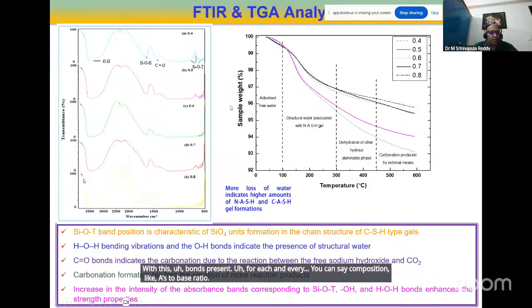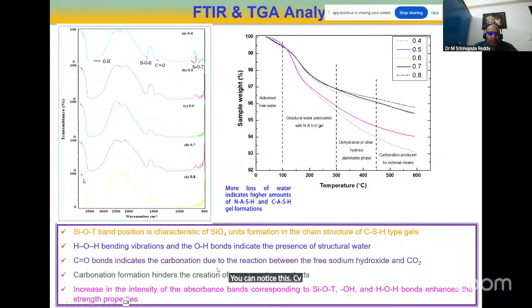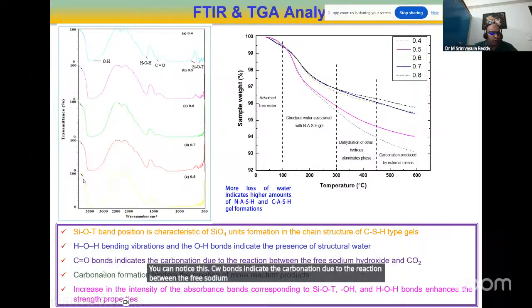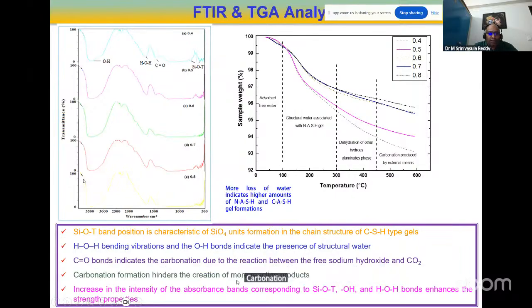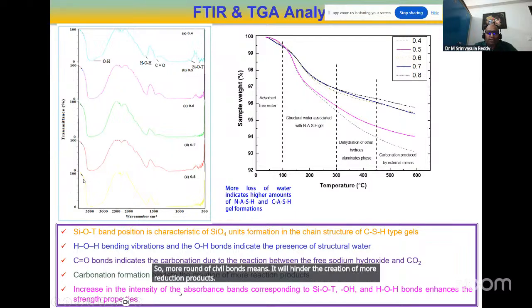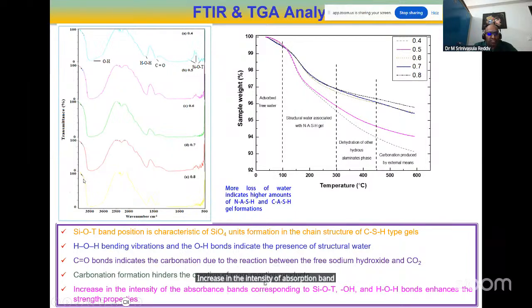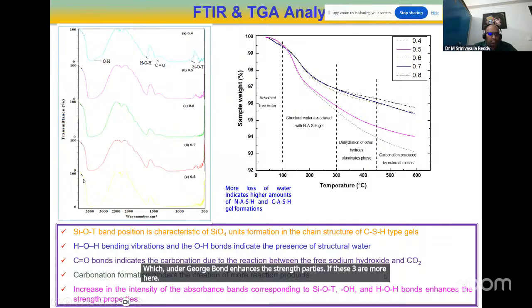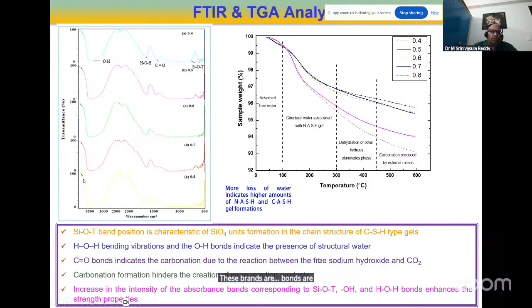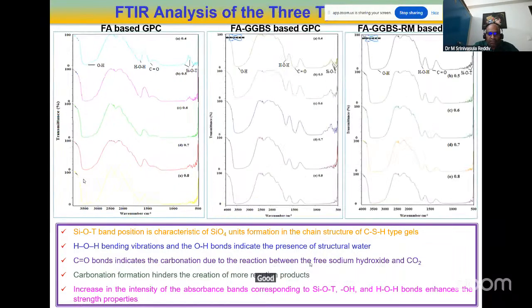You can notice this. C=O bonds indicate the carbonation due to reaction between the free sodium hydroxide and CO2. Carbonation formation hinders the creation of more reaction products. So more amount of C=O bonds means it will hinder the creation of more reaction products. Increase in the intensity of absorption bands corresponding to Si-O-T, OH, and HOH bonds enhances the strength properties. If these three bonds are more here, then we can say that the strength properties also will be good. It is the same for different concretes.